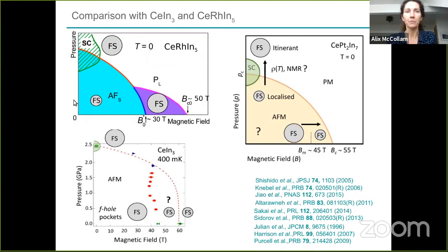So for cerium rhodium indium 5, these measurements of Shishido that I showed, where the effective mass diverges close to the suppression of the antiferromagnetism, this is a transition from a small to a large Fermi surface. This is quite well established in this direction. And this is thought to be an example of Kondo breakdown. So you have a large Fermi surface that suddenly becomes small at this quantum phase transition.